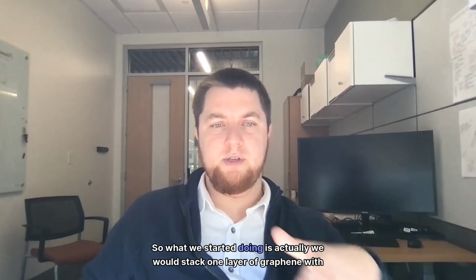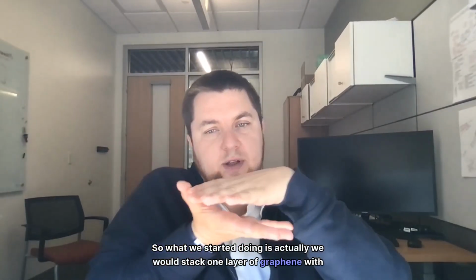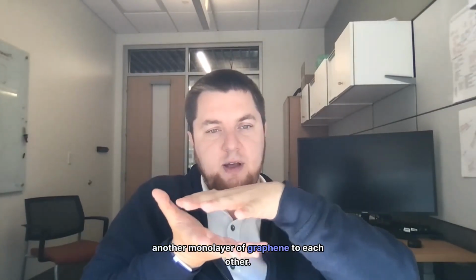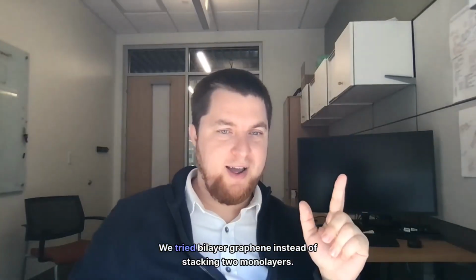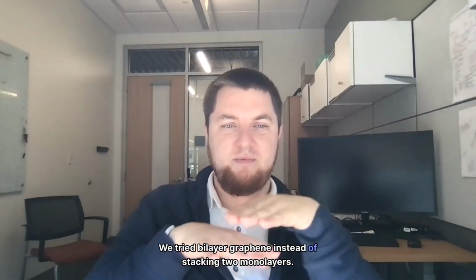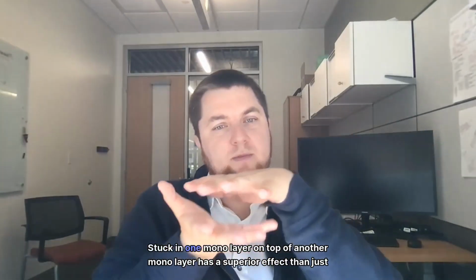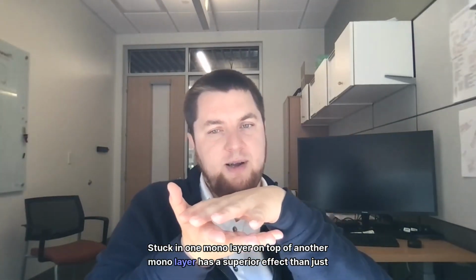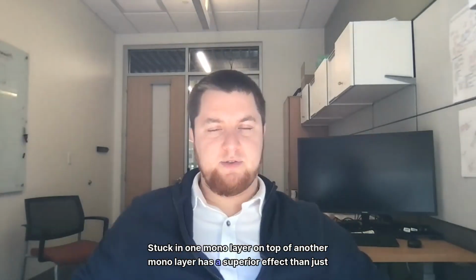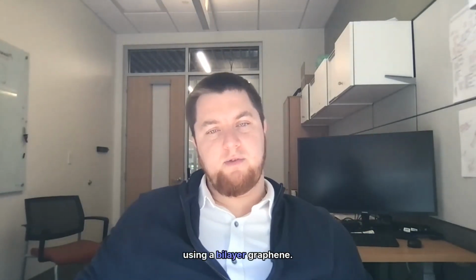So what we started doing is stacking one layer of graphene with another monolayer of graphene. We tried bilayer graphene instead of stacking two monolayers. It doesn't have the same effect. Stacking one monolayer on top of another monolayer has a superior effect than just using a bilayer graphene.